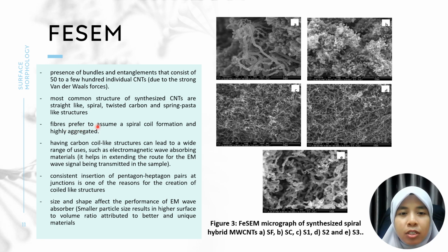So fibers prefer to assume a spiral coil formation and highly aggregated, and then having carbon coil-like structures actually can lead to a wide range of uses, such as electromagnetic wave absorbing materials, whereby it helps in extending the route for the EM wave signal being transmitted in the sample. And the consistent insertions of pentagon-heptagon pairs at junctions is one of the reasons for the creation of coil or fiber-like structure. So size and shape affect the performance of EM wave absorber. Smaller particle size will result in higher surface to volume ratio attributed to better and unique materials.